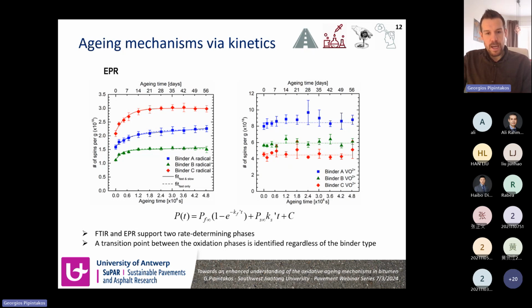What we also assumed is that the organic carbon center radicals that we observed and have captured are probably yielding from the oxygen center radicals, which are short-lived, and most probably the rate of production of the fast rate phase is the governing one for this evolution of the organic carbon center radicals. This means that we can still support two rate determining phases. However, here the fast rate phase is governing for the production of the organic carbon center radicals.